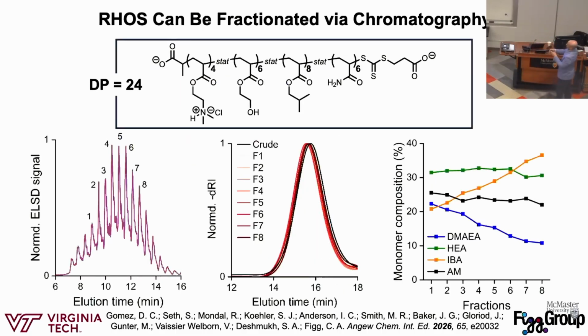So the left one is just showing the HPLC fractions. So we took fractions 1 through 8, and we characterized them by gel permeation chromatography. All of the fractions overlap with molecular weight distribution, so all the fractions are about the same molecular weights, same dispersities, all of that. If we characterize composition by NMR, we see that the fractions increase with hydrophobicity as the fraction number goes on. This makes sense.